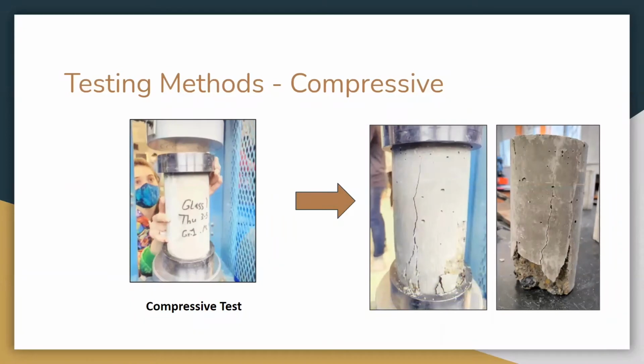The first test we performed was a compressive test, where we put 1 of each sample into a machine that pressed downward on the concrete while recording the load, or weight, the sample could withstand. As you can see from the pictures on the right, we had some pretty interesting fractures in our samples. Here's a clip of one of the more exciting fractures that we saw during testing.